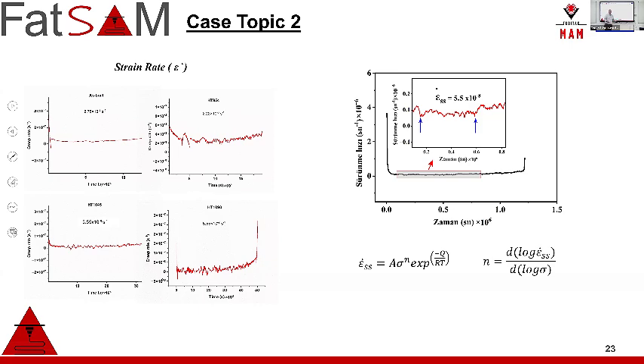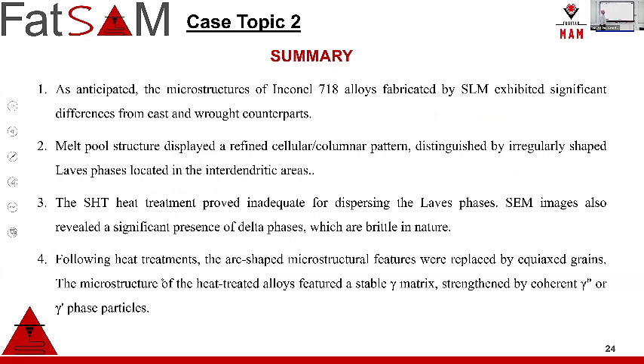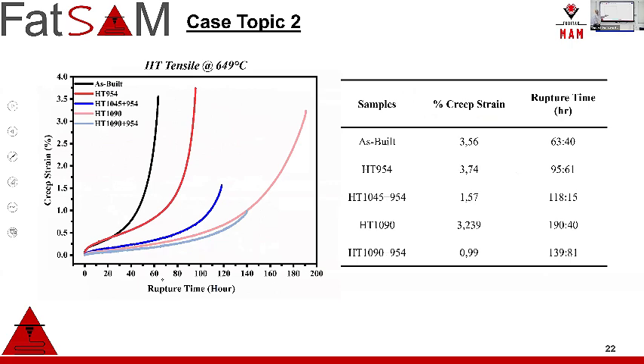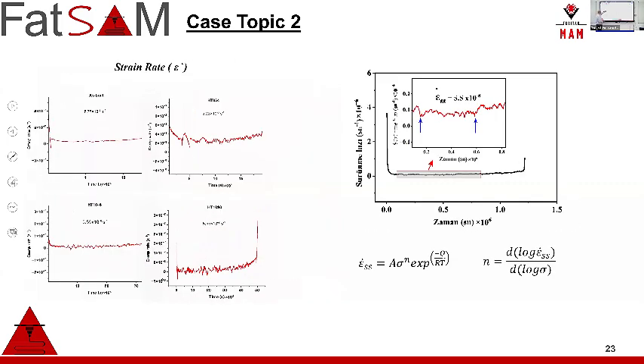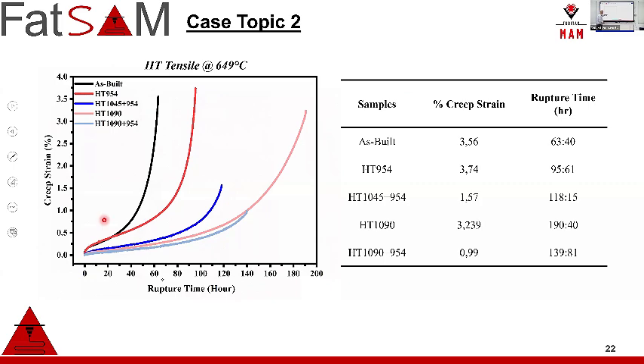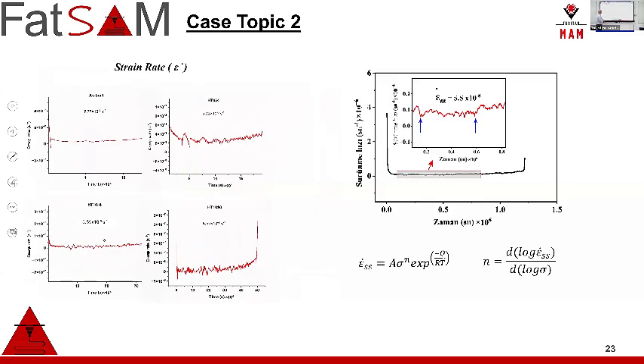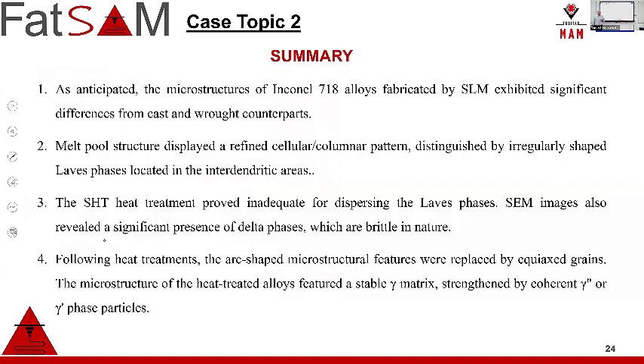in these materials it is very difficult to find the steady state, because superalloys are slightly different from other materials. Why? In general, creep looks like a reverse of the S-N curve in fatigue. You have a primary region, steady state region, and rupture. Let me return this one. There is no steady state region in superalloys. Or, when I say this, because in the last conference in MMC, people didn't like this definition, which is right. Let's say that it's a very short steady state region. That's why we focus on the steady state region. For highly elongated samples, you can see a little bit like HT954, or as built conditions. But rather than this, it is too much noise to calculate the steady state creep strain rate.